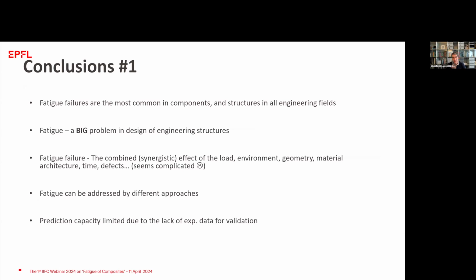So to conclude, I will just go very fast. We know that fatigue is very, very bothersome. It's a big problem in designing of engineering structures. We know that now most of the structures are failing due to fatigue or fatigue-related phenomena, as we said before. Unfortunately, for composites, this investigation is more complicated because we have synergetic effects that are acting all together, and one is affecting the other. We cannot isolate effects as in metals. We have a crack that propagates and leads the material to failure. We know there are a lot of different approaches to discuss about fatigue. And we know that, unfortunately, there is a lack of experimental data to validate these approaches.